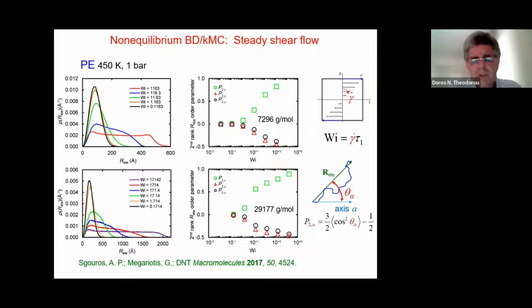So this mesoscopic model can give us a good grasp of these nonlinear viscoelastic properties for longer chain lengths that could not be simulated with atomistic simulations. We have a gain of roughly 3 orders of magnitude in relation to atomistic molecular dynamics when we invoke these mesoscopic simulations.